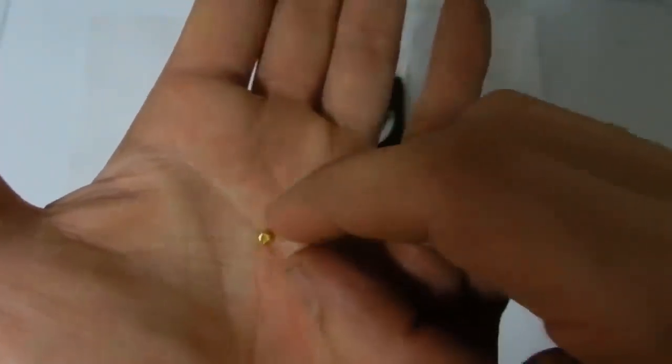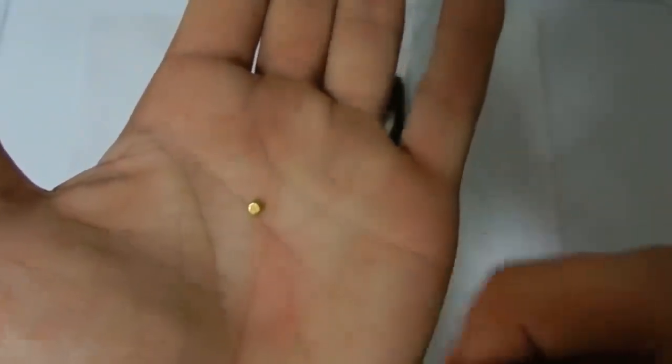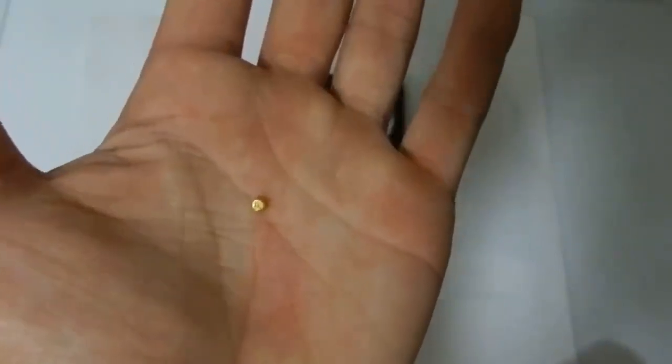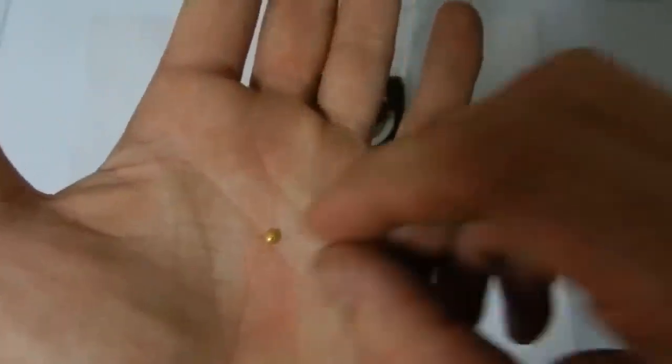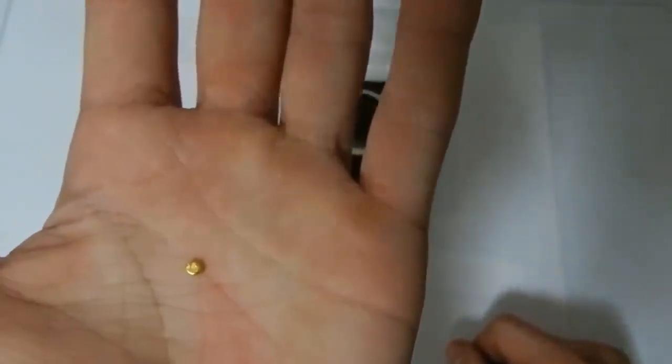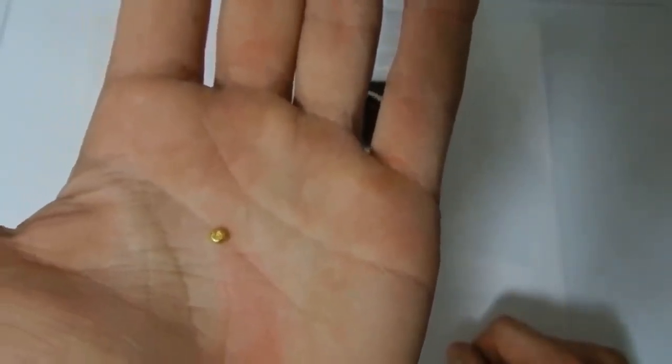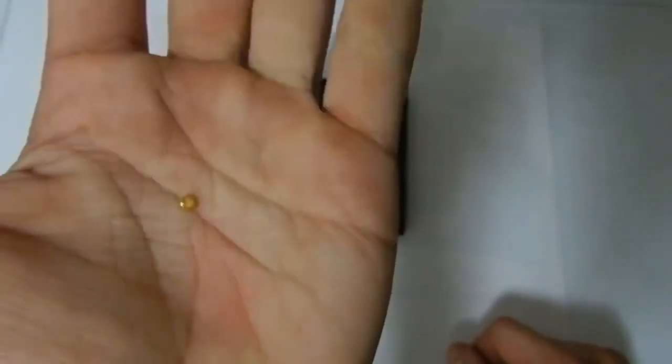This is obtained for 100 g of such contacts, so 0.72 grams of gold. And for 1000, that is a kilogram of contacts, it comes out 7.2 g of gold. But a fairly normal material for processing, especially in this way. Little costly, I think. I also want to say that the content is not always the same, it happens that it is smaller. Before that, I had 10 processors, the output was much less. That is, the content in them is also different, depending on the codes.